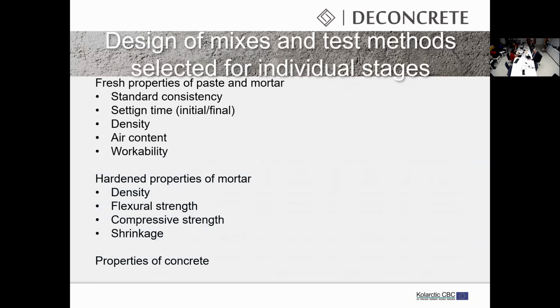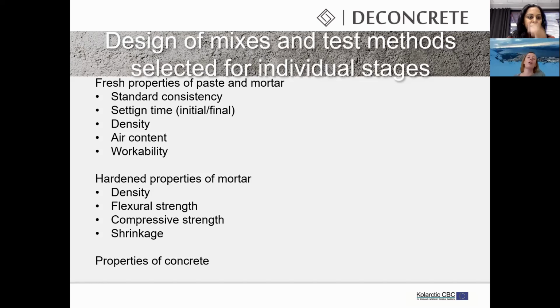Testing methods used during this set of tests for evaluation of supplementary cementitious materials: on fresh mortar and paste, we tested standard consistency and setting time, and on mortar density, air content, and workability. Air content and workability were controlled within a certain range. For hardened properties of mortar, we checked density, flexural strength, compressive strength, and shrinkage of the mixes with 10% replacement.